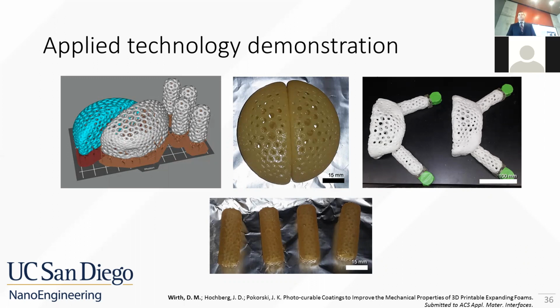The applied technology demonstration we chose for this was to create a foam drone. All the components for this drone fit on a single build plate of the Anycubic Photon. Here's what they look like as printed, and then after expansion. After they're glued together with the S100 resin, you can see that they're dramatically larger than the original build plate.